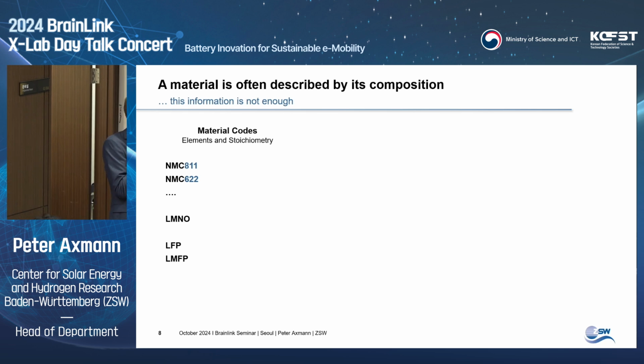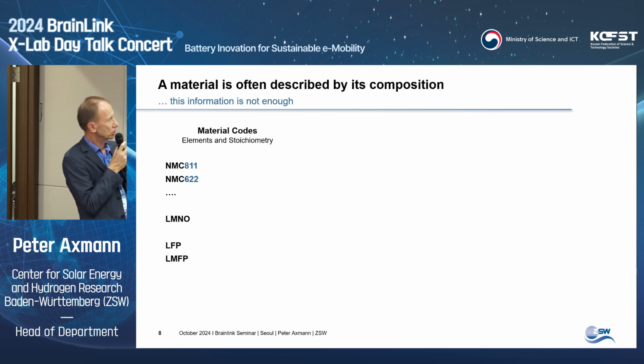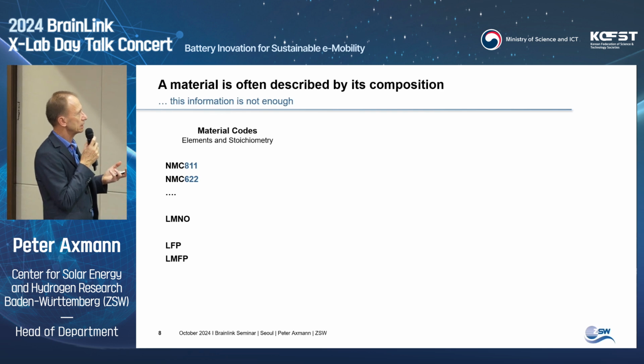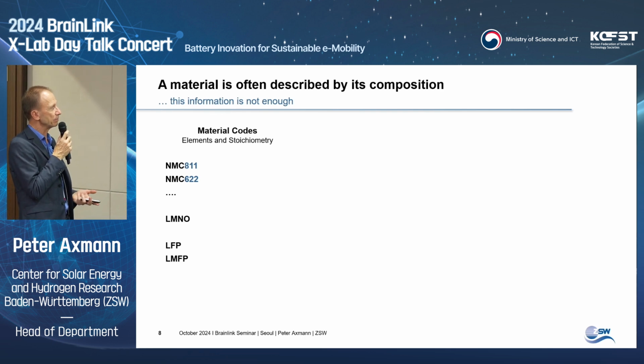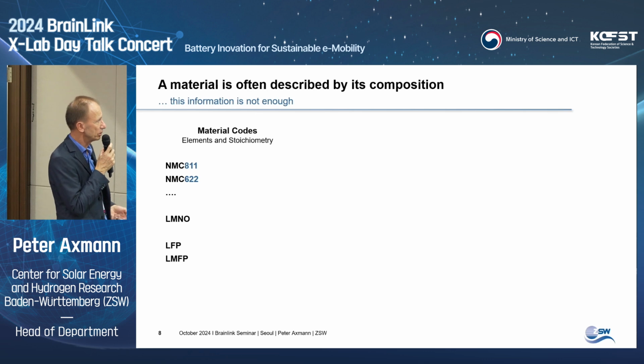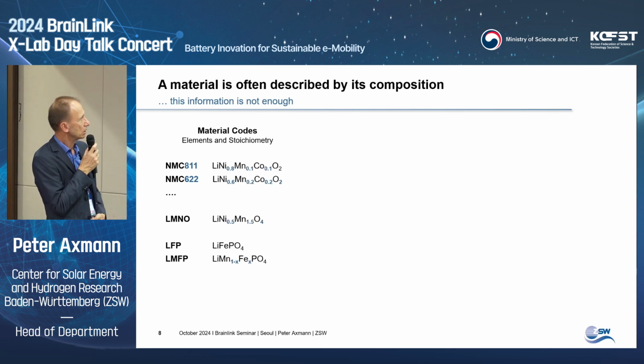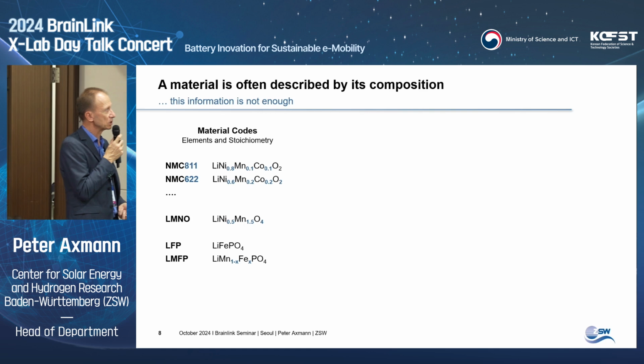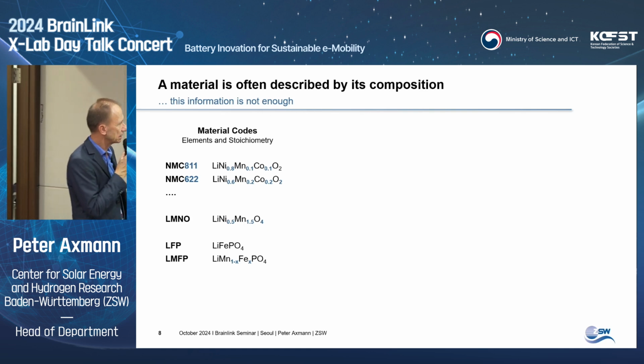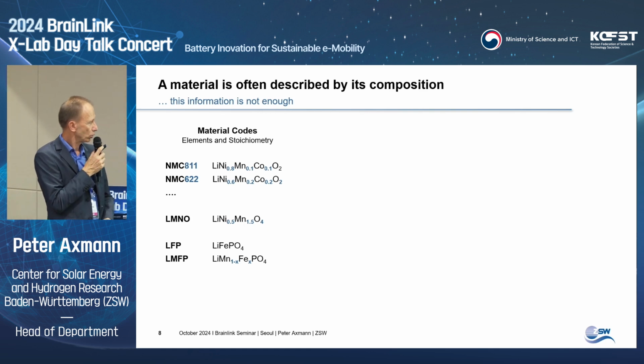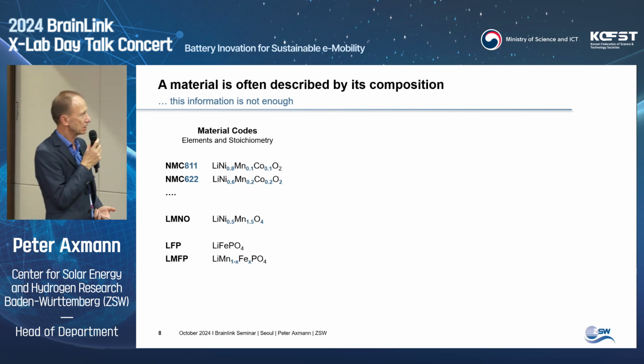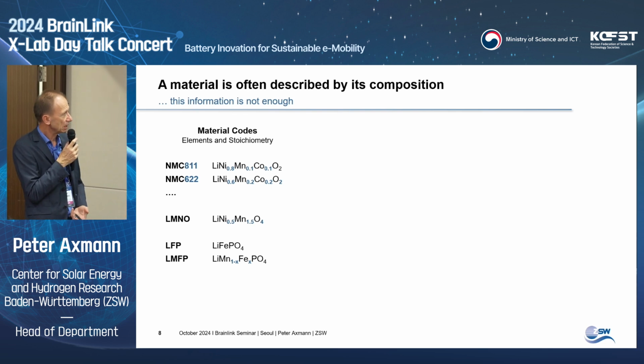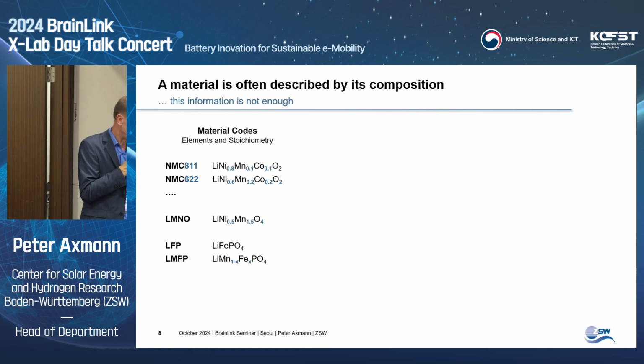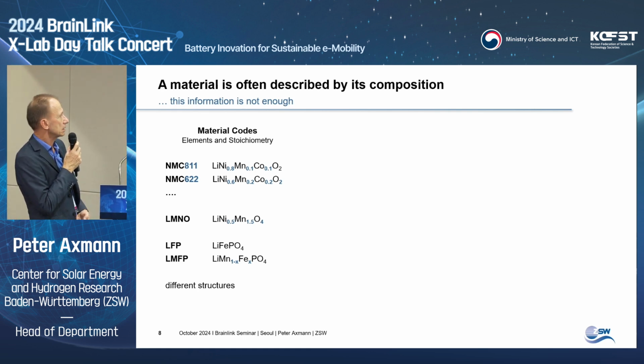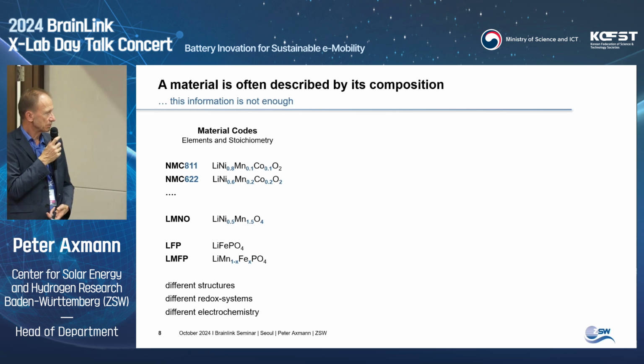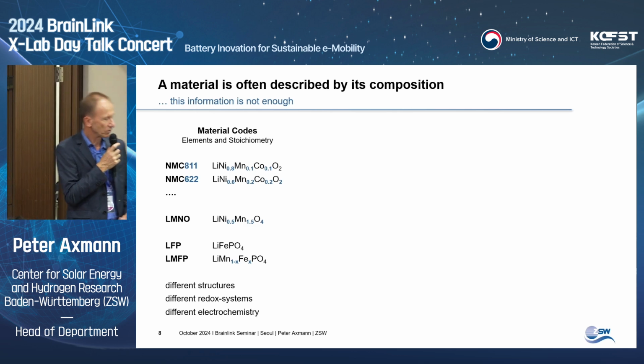So what I want to come to now is that a material is often described just by its composition. There are material codes which relate to the elements you use, like NMC, nickel, manganese, cobalt, and the stoichiometry you use, like 811, which means 80% nickel, 10% of manganese, and 10% of cobalt, and so on. We have the LMNO, which is a high voltage spinel containing lithium, nickel, and manganese oxide. You have the LFP, the olivine structure, and LMFP. And these have different structures, different redox systems, different electrochemistry, and different aging phenomena.